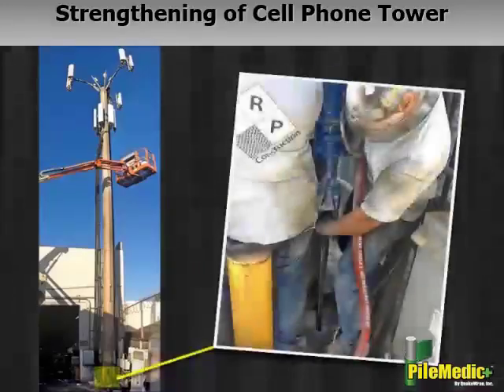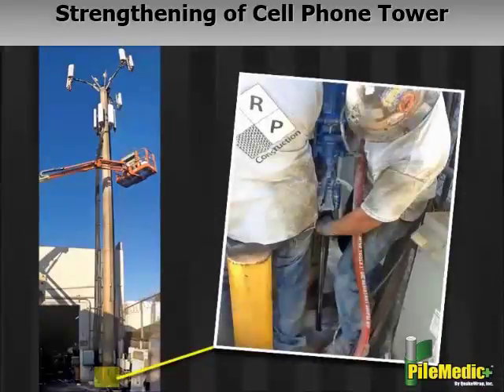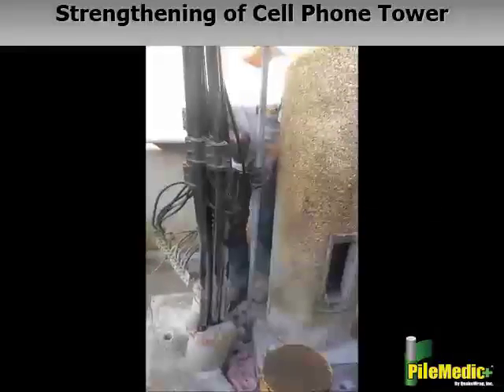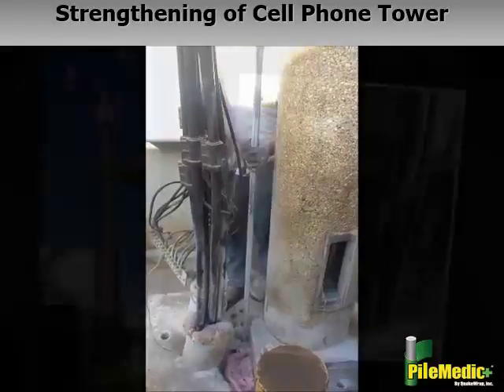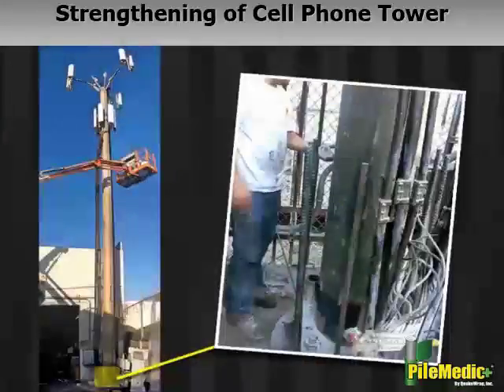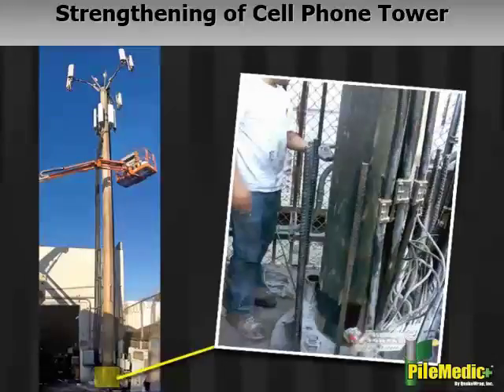1. 14 feet, or 4.25 meters, deep holes with a diameter of 1.25 inch, or 32 millimeters, were drilled into the foundation. Steel reinforcing bars were epoxy anchored into these holes and extended above the foundation. Such deep drilling is not common in all repairs, but it was required at this specific site.